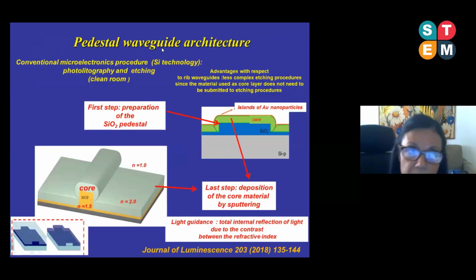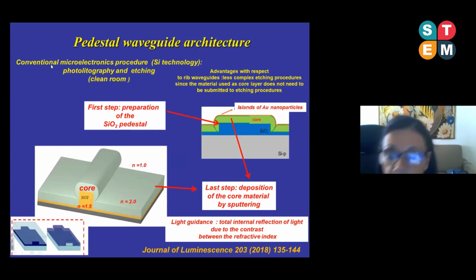To produce these pedestal waveguides we use silicon technology, I mean the conventional microelectronics procedures that make use of lithography and etching, all of them performed in clean room. And we have two main steps for that. The first step is the preparation of the silicon dioxide pedestal, shown here in blue, and the last step, in green and yellow, the deposition of the material of the core followed by the deposition of gold, both performed by the sputtering technique.